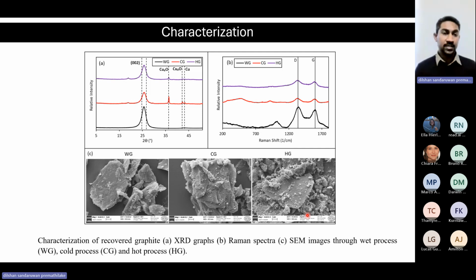the clean XRD pattern. This is due to the non-availability of any impurities in this graphite. However, when I tried to do this analysis through SEM images, I could see that a minor amount of impurities can be seen in the wet graphite, but compared to the cold graphite and the hot process graphite, it's quite low. Which means the quality of the graphite is quite better in the wet process derived graphite.